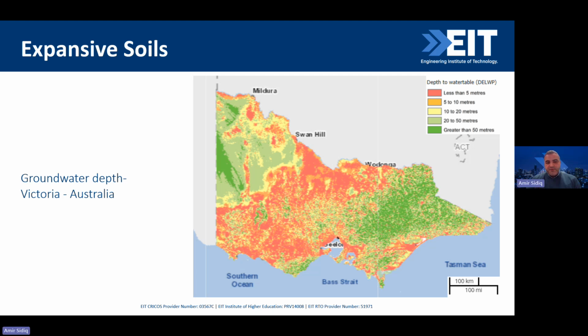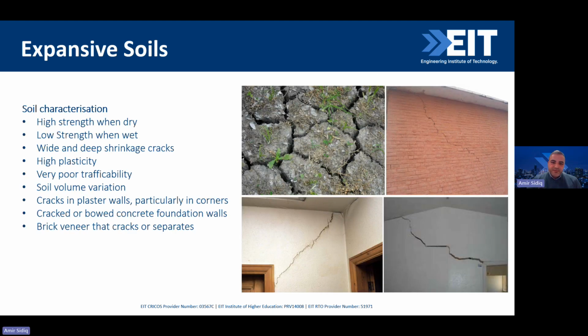So this is some of the damages. Basically, when the clay is in its dry conditions, it's very strong, and when it's wet, it becomes very soft. The structure actually sinks through the soil material. Some cracks can develop within the mortar along the brick layering, but they generally come as a diagonal from corner to corner. The reason for that is the shear stresses. All these diagonal cracks, or quite high angle cracks, are actually from the shear stresses.